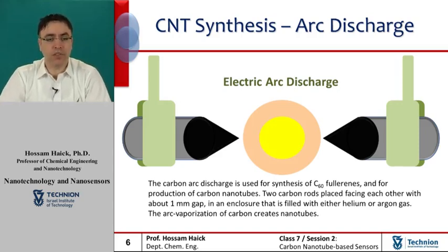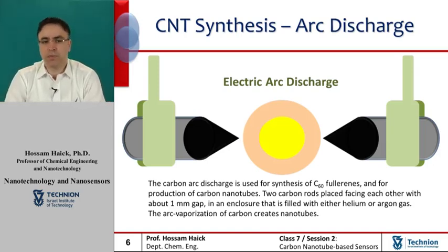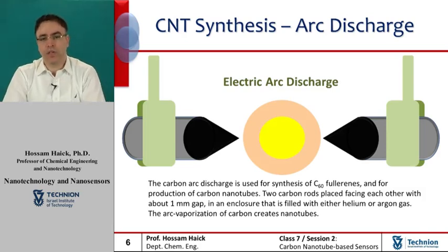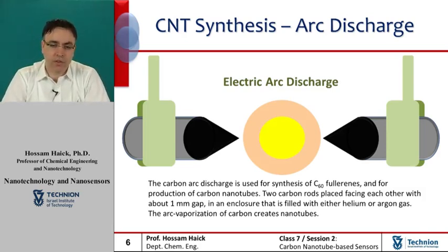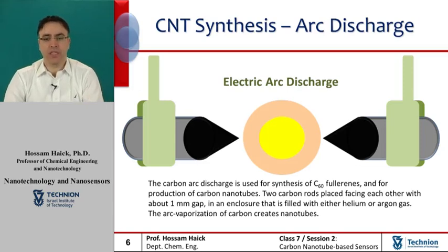During the sublimation, the pressure runs very high as carbon atoms are ejected from the solid. These atoms migrate towards colder zones within the chamber, allowing a nanotube deposit to accumulate onto the cathode. The type of nanotube that is formed depends critically upon the composition of the anode itself. This technique usually causes the growth of carbon nanotubes with fewer structural defects in comparison with the other techniques.